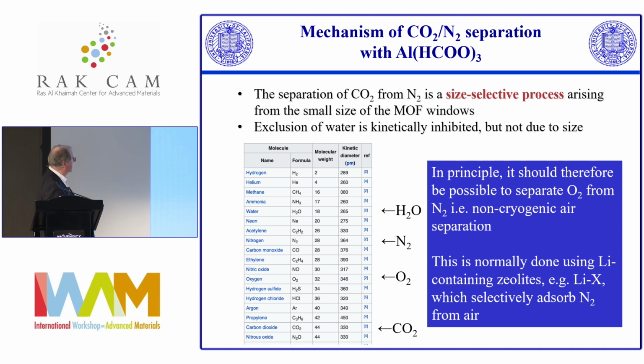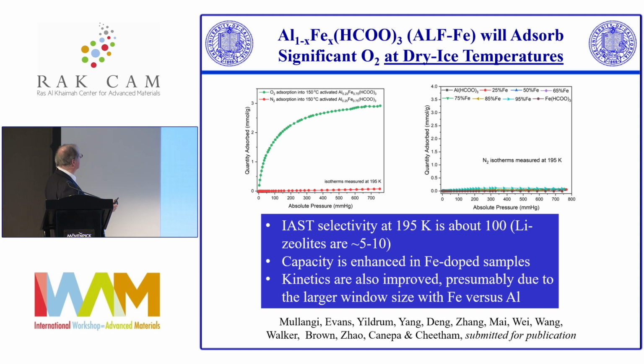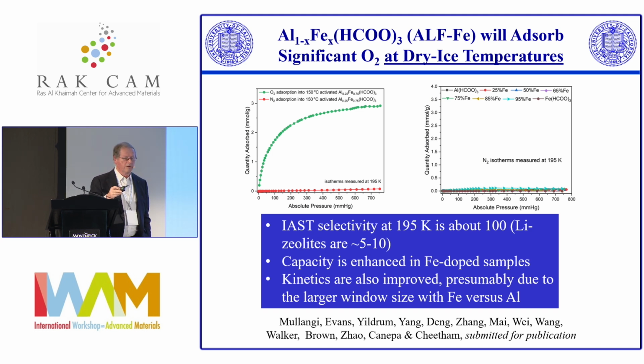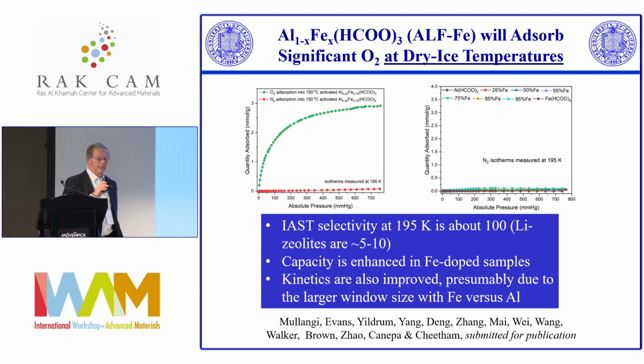So we tried this, and it works very nicely. Especially, the adsorption is quite low at room temperature, which is not too surprising, as you'll see in a moment. But the adsorption at dry ice temperatures, about 195 K. This is the nitrogen adsorption at dry ice temperatures, and this is the oxygen adsorption at dry ice temperatures. So it's got a selectivity of about 100 for oxygen over nitrogen, which is huge in this area. The commercial zeolites have a selectivity between 5 and 10 for nitrogen over oxygen.